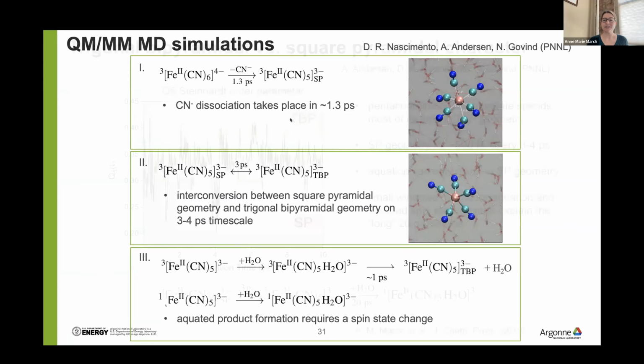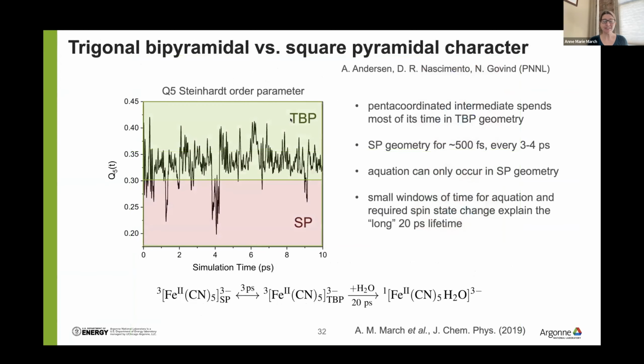So here's what's happening. They did some more analysis. That pentacoordinated species is spending most of its time in the trigonal bipyramidal geometry, but then every 3 to 4 picoseconds, it has a small window of time where it's in a square pyramidal geometry, and this kind of opens it up to allow space for a water to approach. And so it's only those small snippets of time when aquation can occur, and this kind of explains the long time scale.